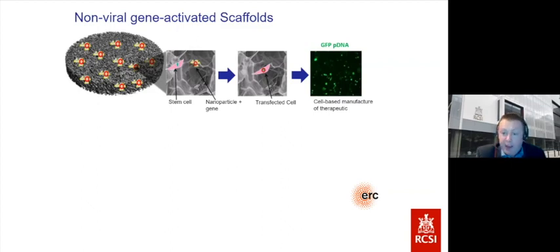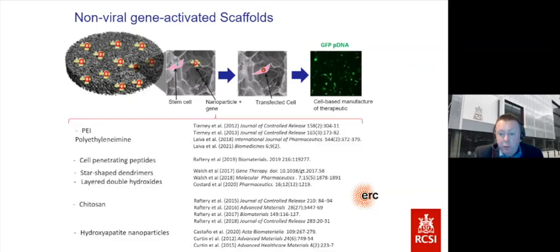If it's, for example, a plasmid DNA we're delivering, or a messenger RNA, or they silence it if it's something like an siRNA or a microRNA that we're delivering. So if it's a bad effect, we can shut it down. And what we now have, next slide, please, is a whole series of different types of nanoparticles for different indications. And we can control the release kinetics of these cargoes, these genetic cargoes, depending on the composition of the particles we use. And I'm just giving some examples of these particles on this slide.